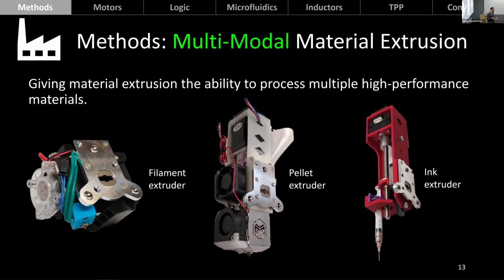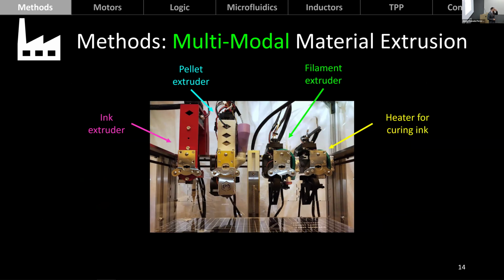And how do we do that? Well, we have to customize this printer that I mentioned earlier, the tool changer. And the way we did that was we kept one filament extruder because there are still filaments that we are interested in using. And we swapped the rest, one for a pellet extruder and another one for an ink extruder. This is the final lineup that we have in this printer. So we have an ink extruder, a pellet extruder, a filament extruder, and a heater for curing the ink that comes out of the ink extruder. And with this, we are able to access the 3D printing of high performance materials.